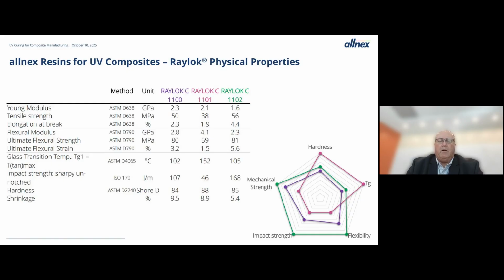So while we do make a lot of customer-specific materials, these are the generic Rayloks that can be sampled or purchased. And the Raylok C1100 is a very basic material. The Raylok 1101 is a high TG material. You can see the 1100 has a glass transition temperature of around 100. The 1101 is about 50 degrees higher at 152 degrees C. Raylok 1102 is more of a tough material, and you see that through the high impact strength of 168 versus the other two, which are much lower.